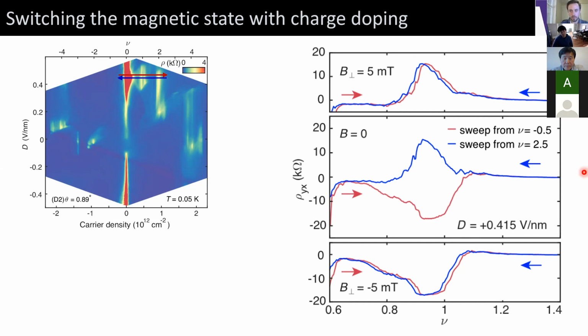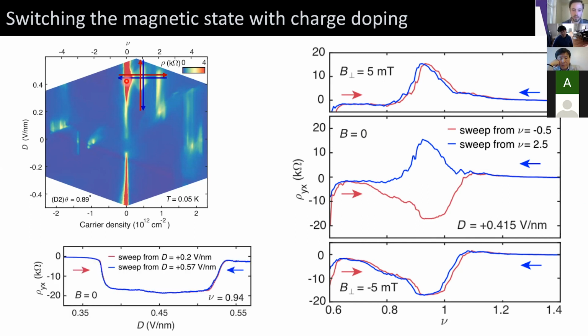So if we sweep from large doping, we get the positive magnetization state. And if we sweep from small doping, we get the negative magnetization state, all in the absence of magnetic field. We can do the same thing for displacement field, but it doesn't switch in the same way. So this is really quite a curious phenomenon.